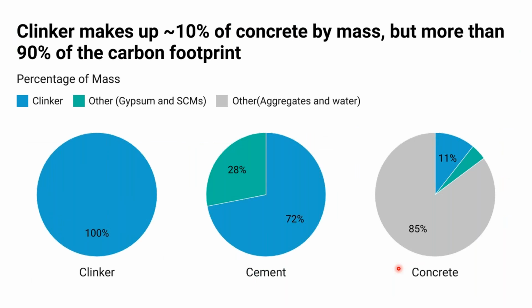So if you look at it, cement, a clinker, makes up about 10% by mass of concrete. So if you look at this here, basically you start off with clinker. That is a basic material that we use for making cement. And by the time you come to concrete, its percentage is diluted to about 10%. So that is how much clinker goes into concrete. But if you look at the carbon footprint of this concrete, the clinker makes it about 90% of the carbon footprint of concrete. And carbon is the one word, it has become a dirty word.